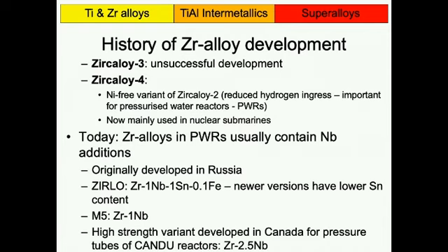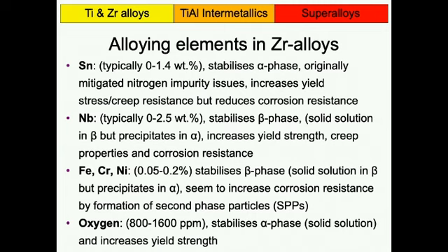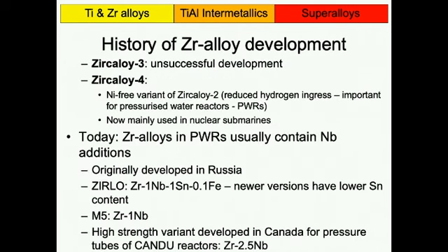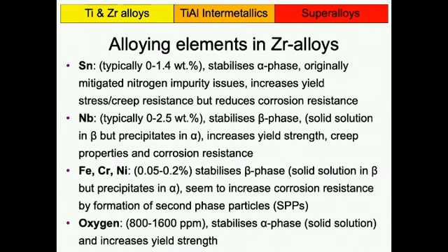And that's why something like this is possible now. Framatome producing an alloy which actually has no tin left in it, simply because the nitrogen contamination has been driven down very dramatically. But tin increases the yield strength and creep resistance. So you need some strength in that material, and tin helps. However, it reduces corrosion resistance. It really does. There have been a lot of studies showing that tin accelerates corrosion, and that's why you find that Framatome has actually reduced tin. And even Westinghouse now, they have newer versions of this where they drive down the tin content for that reason.